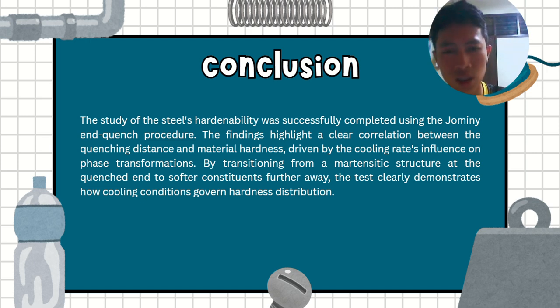At the quench end where the cooling is fast, we obtain a martensitic structure, which provides the highest hardness. However, as we move further away from the water, the cooling rate decreases and the steel becomes softer. This test clearly proves how cooling conditions govern the hardness distribution throughout the material. Therefore, understanding this correlation is vital for choosing the right heat treatment in engineering.